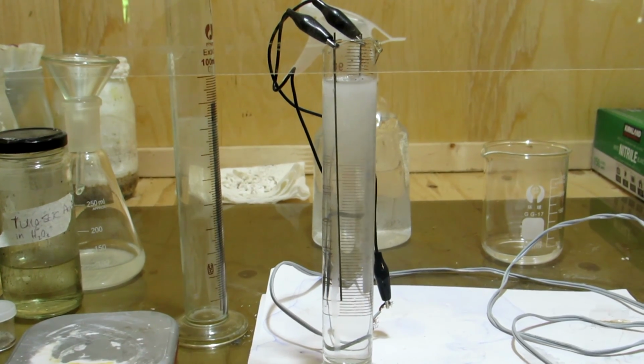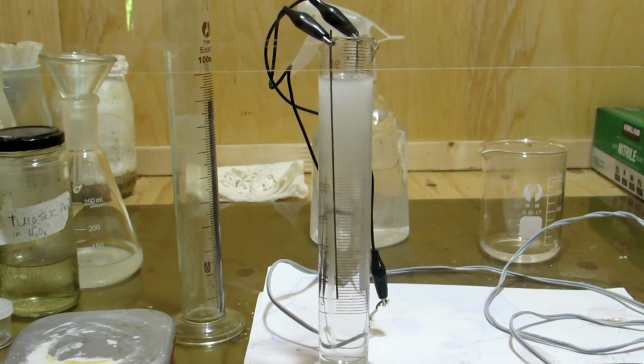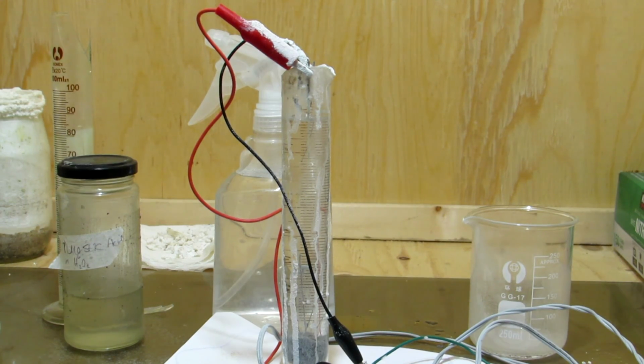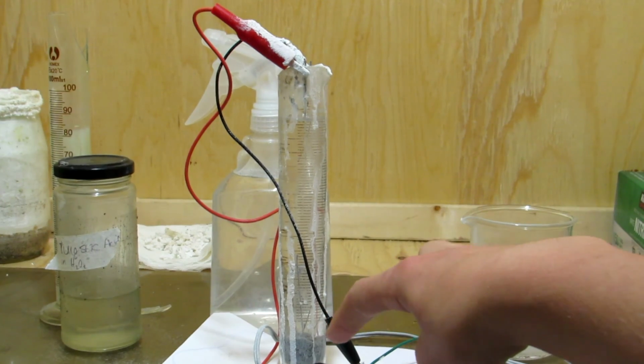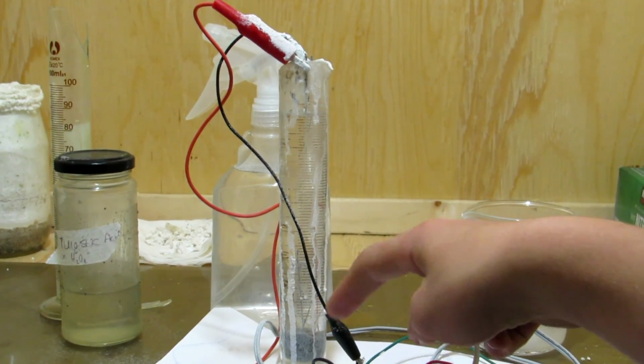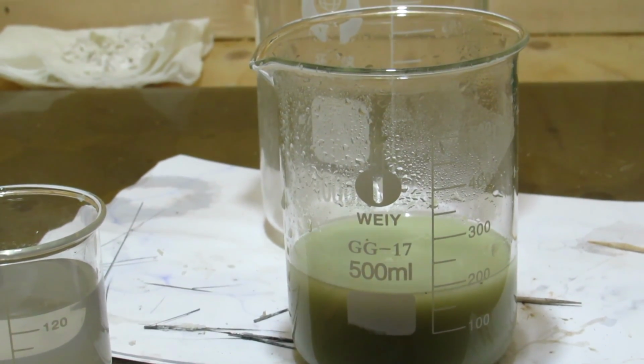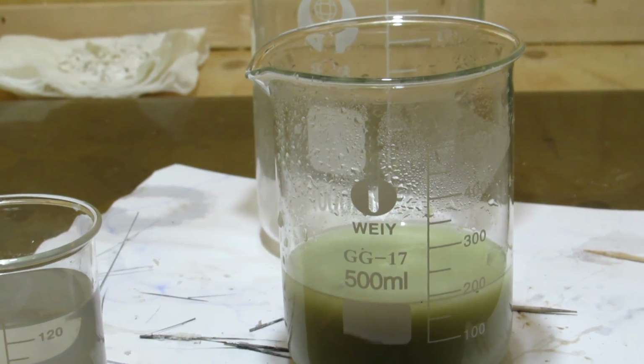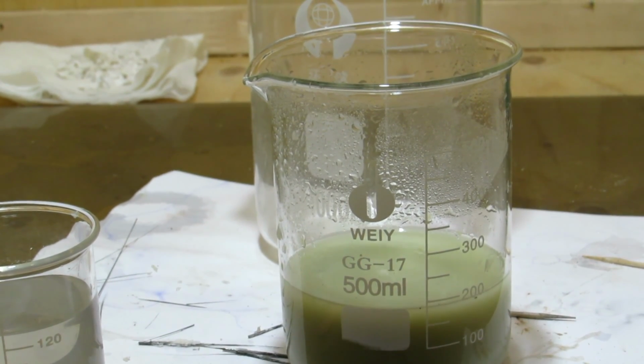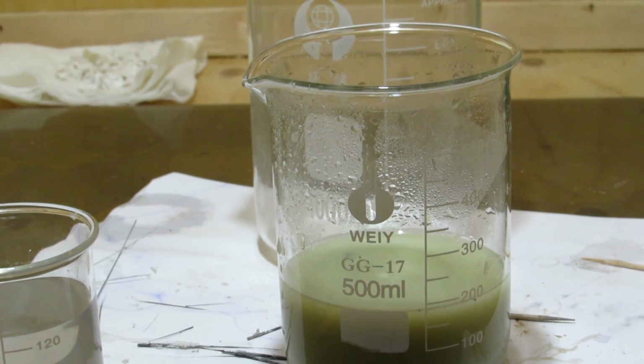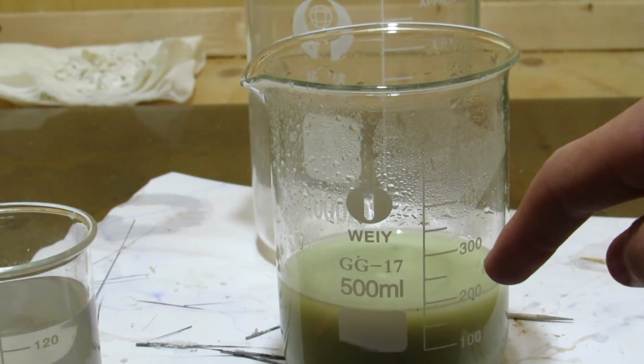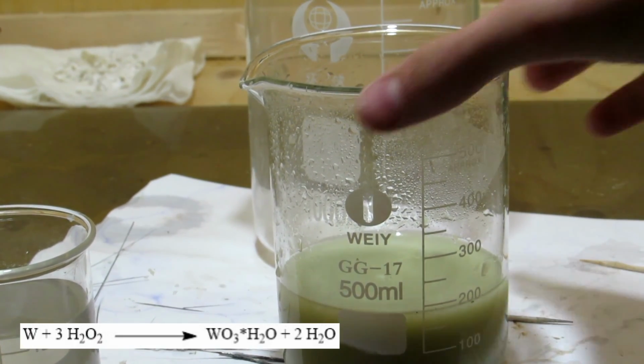As the rod dissolves, the thorium dioxide falls to the bottom and settles. After approximately 6 hours, 9 of the tungsten rods had dissolved. Some bits of the tungsten rods flaked away and settled to the bottom, so not all of the tungsten was dissolved, however. The thorium dioxide also contained bits of undissolved tungsten, so the large chunks of rod were removed, and the thorium dioxide was rinsed, and then added to about 200 milliliters of 30% hydrogen peroxide to finish dissolving the remaining tungsten.